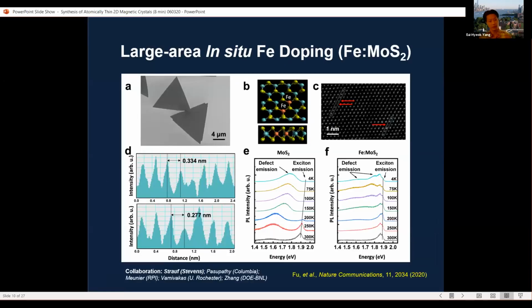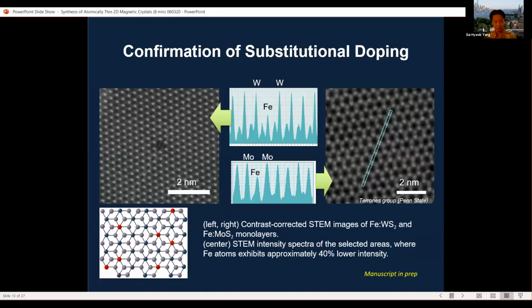For example, in figure A here, the large area growth is important. First we start with growing a single crystal monolayer, an isolated one, as shown in A on the top left. Then with further growth we get these merged layers. Eventually you get a continuous film, basically a continuous monolayer with all this iron doping. This is collaborative work, so we do the synthesis, but for characterization we send our samples to various labs. So that's what we do here.